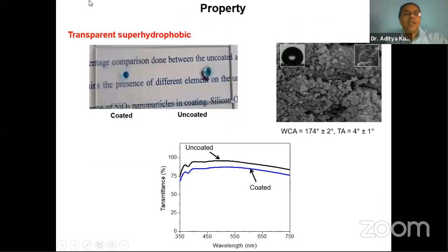Here is a transparent superhydrophobic surface. As you can see, this side is an uncoated glass surface. Glass is transparent in nature, so we have taken glass as the substrate to make the superhydrophobic surface. This side is the uncoated part, and this side is the coated part. So we can create a transparent superhydrophobic coating. With the superhydrophobicity, water will form a spherical shape, and transparent means we can see through it.